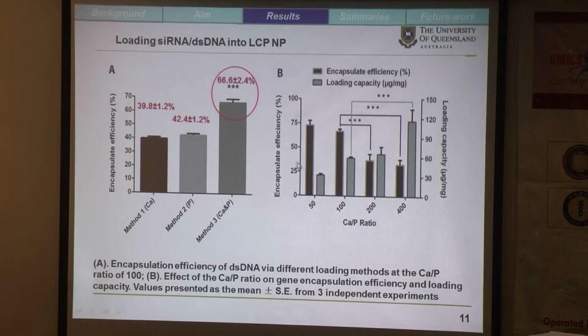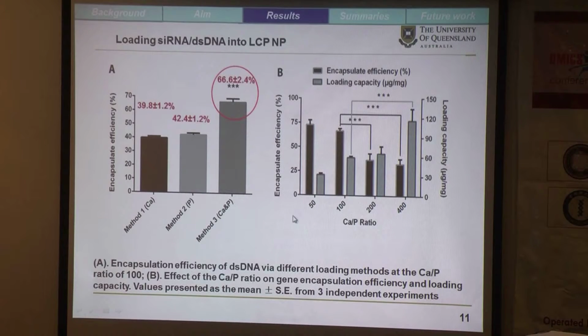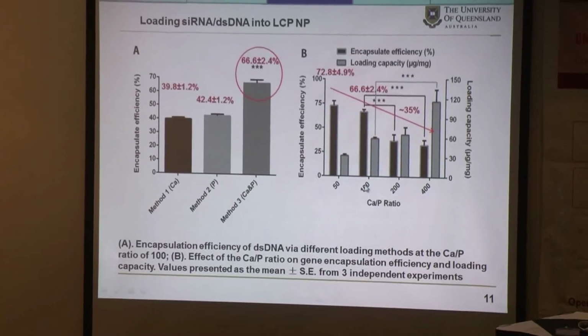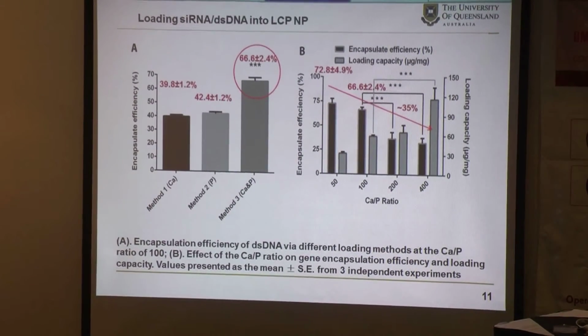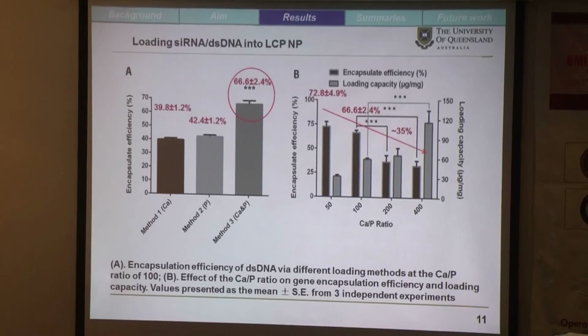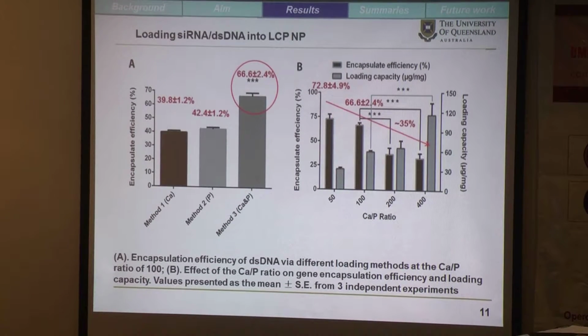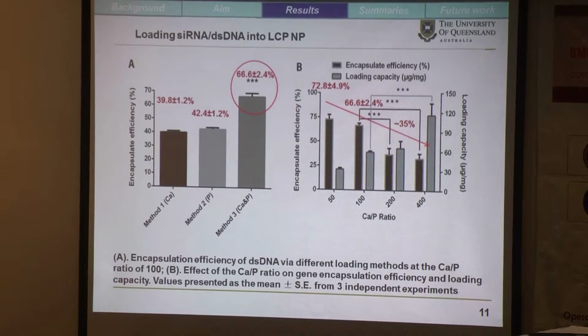As shown in figure B, the encapsulation efficiency of LCP prepared at the molar ratio of 50 and 100 were significantly higher than that of the LCP prepared at a ratio of 200 and 400. In addition, the loading capacity increased with the increase of the molar ratio. This data suggests the calcium to phosphate ratio is critical in controlling the encapsulating efficiency of the LCP nanoparticle.